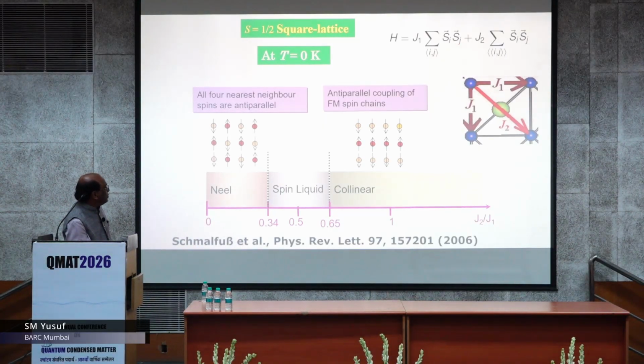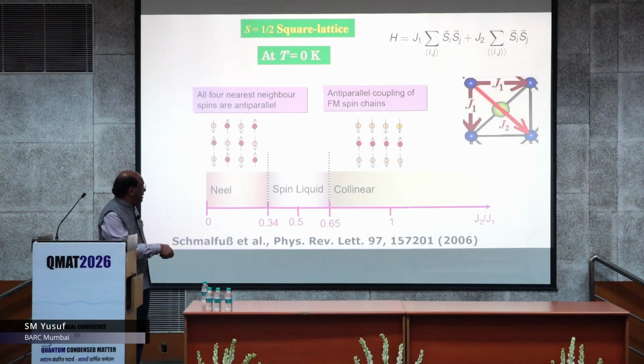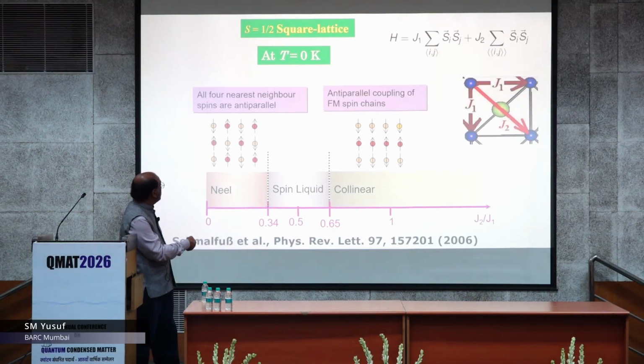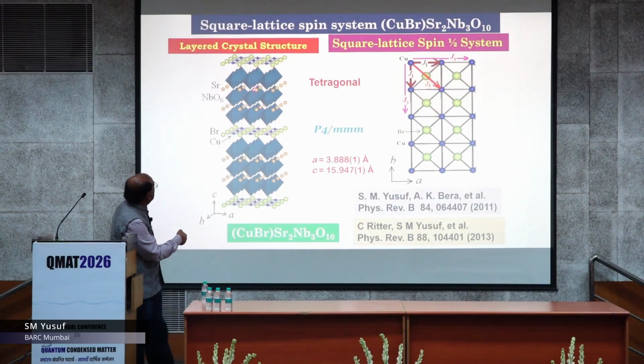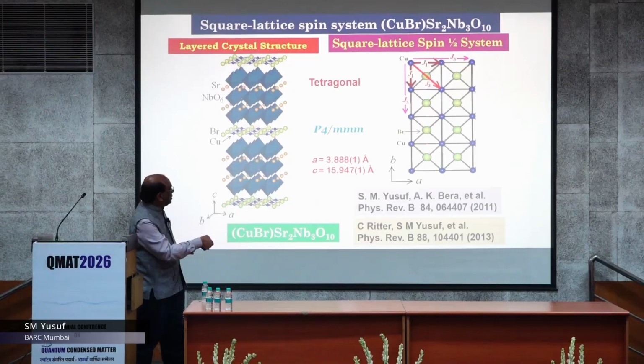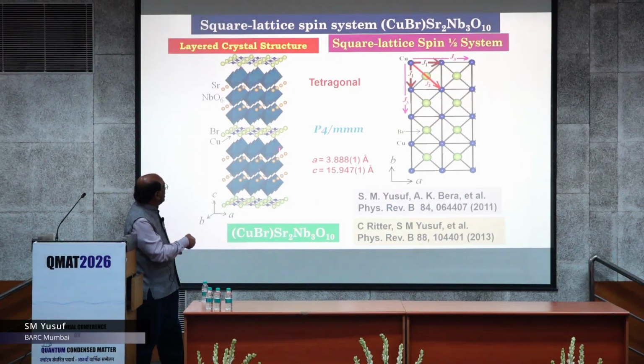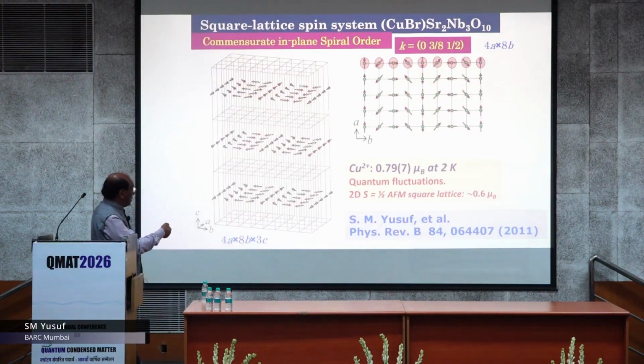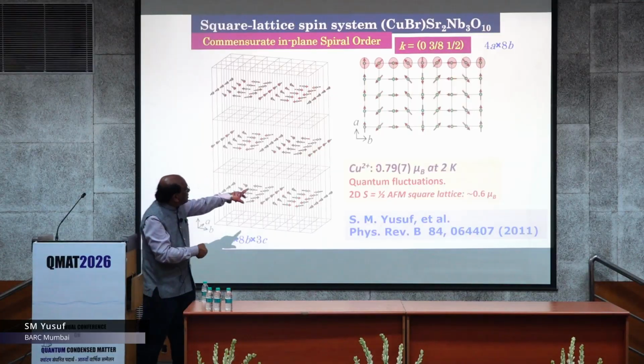Depending upon J2 by J1, one can have spin liquid, in this theoretical paper they published. And then this is one system we work on, where the copper forms a square lattice, and there are both J1 and J2, and here again this is the separation between two magnetic lattices. So copper forms the square lattice in this system, and this is the magnetic structure.